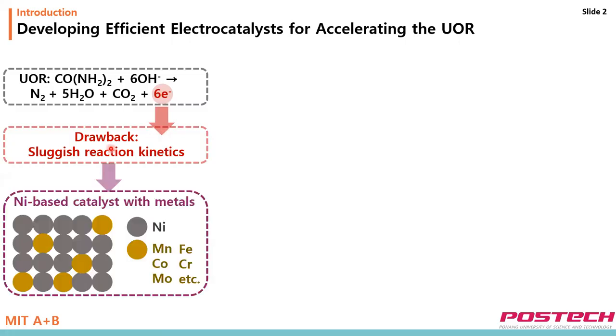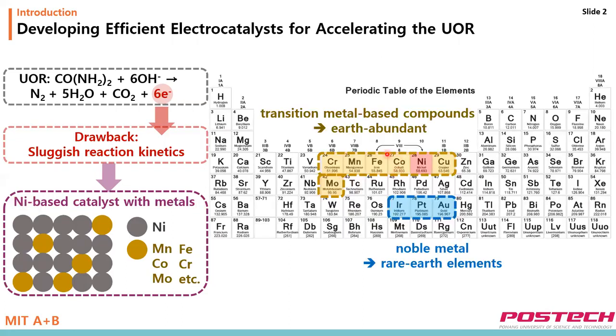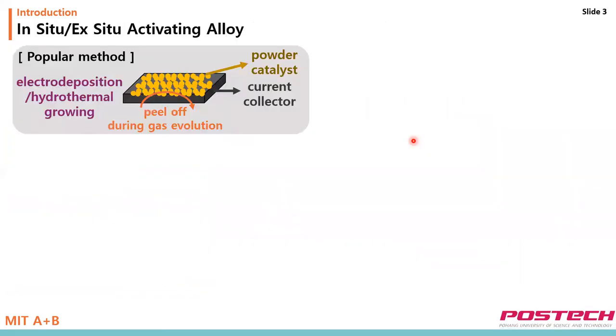Many researchers found that nickel is the best electrocatalyst. Nickel is also an abundant material, so it is available. And even compared to noble metal, nickel has better UOR performance. A further design strategy of catalyst is the incorporation of additional metallic elements. It can enhance nickel-based catalyst through the bimetallic synergetic effect.